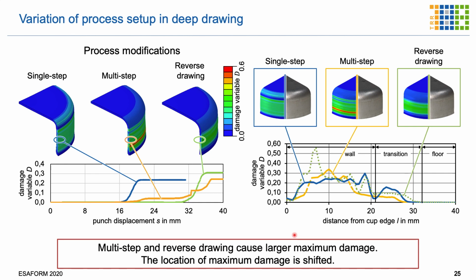Here are the results. Now, just consider this right figure. This is the single-step deep drawing process, the multiple-step forward process, and the reverse multiple-step deep drawing process. What we see on these figures is the damage distribution, and you see that the multi-step process brings damage at a different location than the two other ones.